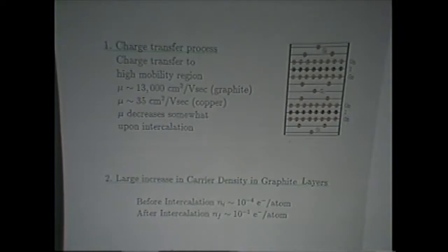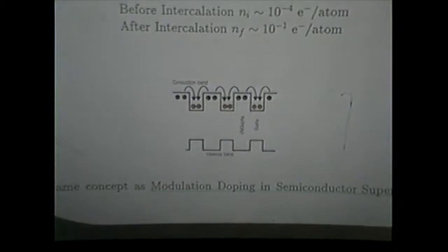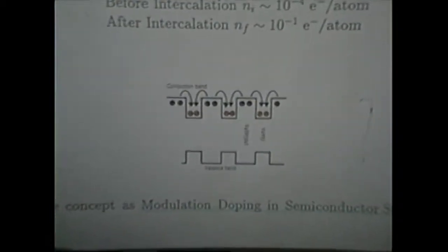And that's why an intercalation compound does have a high, it doesn't have a whole lot of carriers, but it has a high conductivity. In fact, it is said, and some people claim they can make compounds that have conductivities higher than copper at room temperature. So now the reason that works, again, with small carrier concentrations, is that each carrier has a high mobility. And exactly the same concept is used in modulation doping of semiconductor superlattices, where you have a wide gap semiconductor, which you dope, and the electrons will be transferred into these lower energy states into the low gap semiconductor, gallium arsenide, where there are no impurities, there are no scattering centers, so that you have the carriers and you have the high mobility and you get high conductivity in that way.